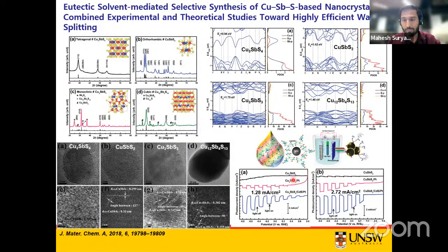So you can see both bare Cu3SbS4 and CuSbS2 show negligible photocurrent density towards the water splitting reaction. That means these compounds are not able to perform the water splitting reactions very well. But with the addition of the platinum catalyst on both photocathodes, you can see there is a slight improvement in the photocurrent density. Again, the performance improvement is not that drastic.